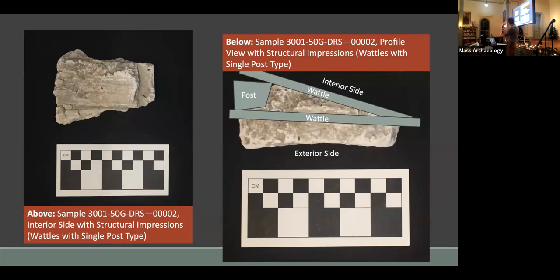With this structure, the wattle and tabby daub structure, a wooden frame consisting of flexible square wattles woven between upright stakes, interspersed between these load-bearing posts, was first erected, and then the tabby was worked into the frame, filling gaps and forming a solid wall until the wall reached the desired thickness and was then smoothed to form a flat exterior surface. The difference between construction techniques is reflected in the material's composition, with cast tabby characteristically containing whole oyster shell and less binder compared to the tabby daub, which contains more binder and small crushed particles of oyster shell acting as a coarse aggregate.